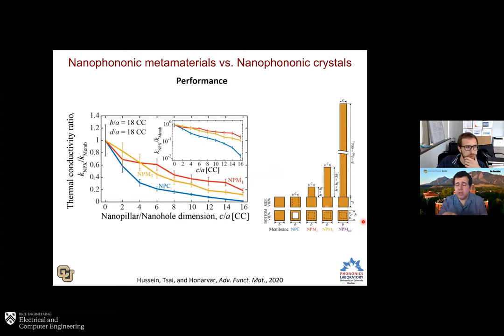This hole can provide some scattering, but it also primarily can give you Bragg scattering, so coherent effects. That also reduces the group velocities, but definitely not as effectively as the pillar, because the pillar provides you with an opportunity, as you add more height, to feed in more effect through these couplings. To test this, we're showing you here from simulations thermal conductivity reduction compared to a base membrane versus how much area coverage of hole or pillar, if you look from the top, we add to a base membrane. You see in red is a membrane with a short pillar, and orange, a slightly larger pillar.